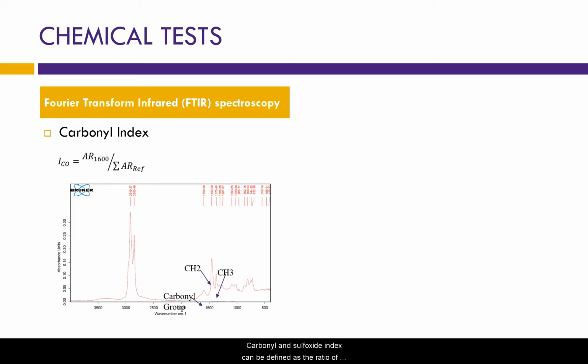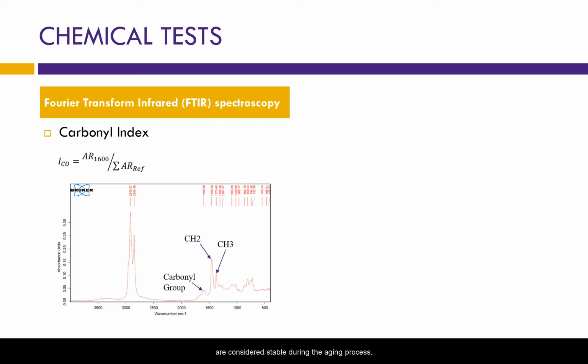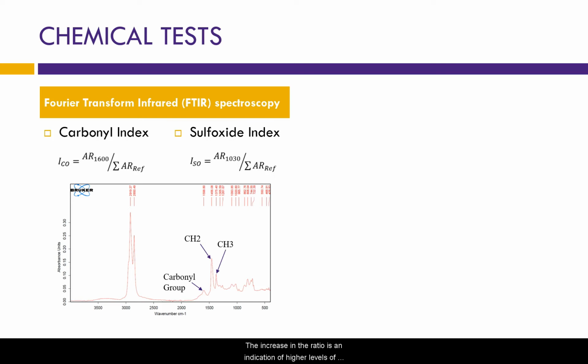1030 peaks. Carbonyl and sulfoxide index can be defined as the ratio of area around these peaks divided by a reference area. The aliphatic group is usually selected as a reference group since they are considered stable during the aging process. The increase in the ratio is an indication of higher levels of oxidation and therefore a stiffer binder.